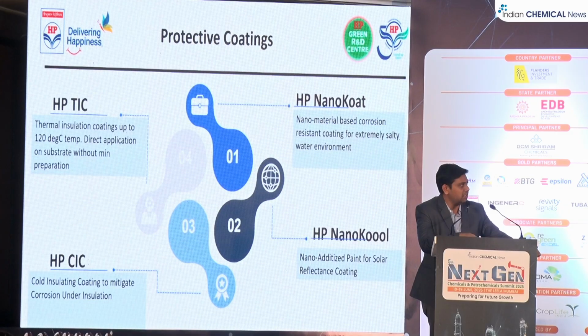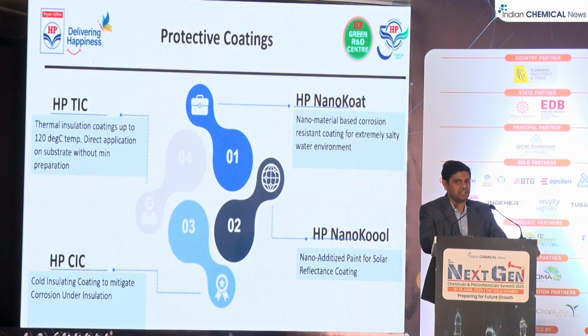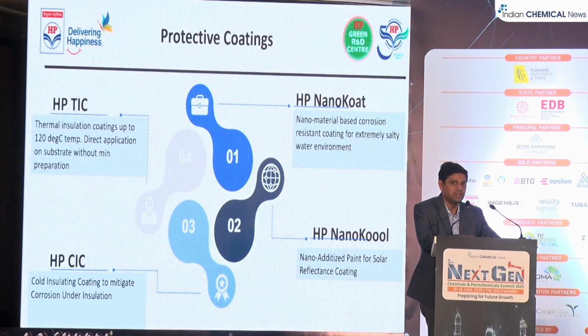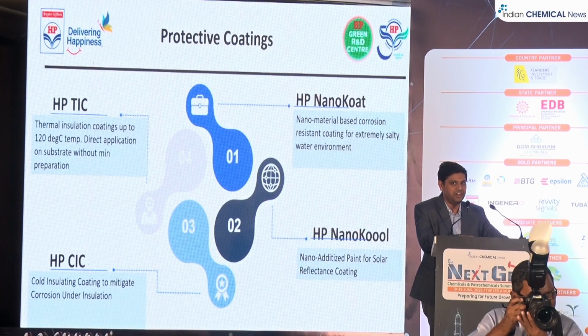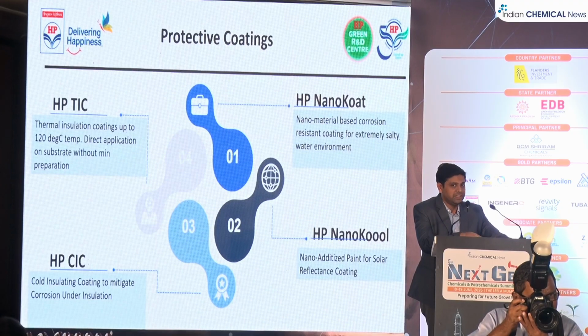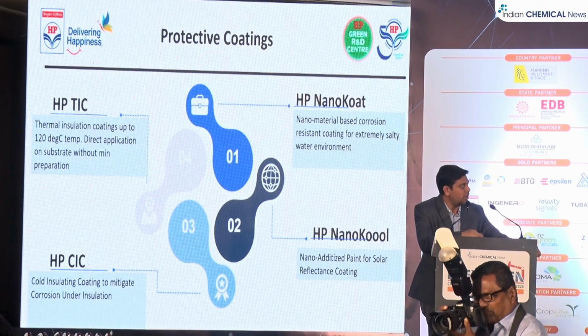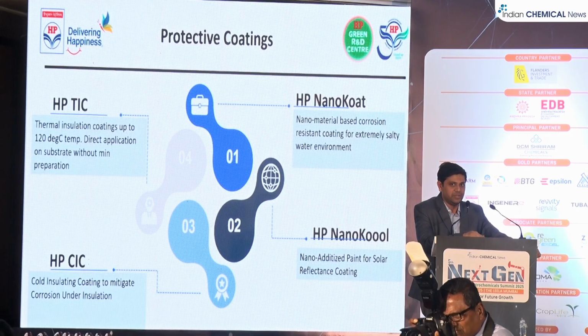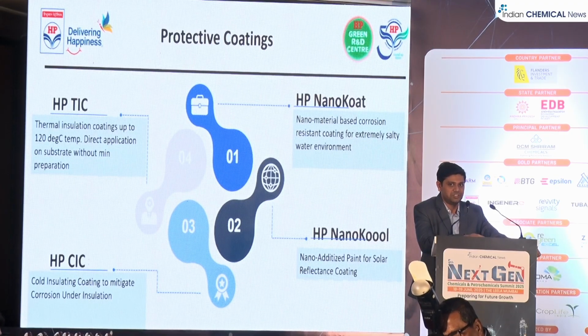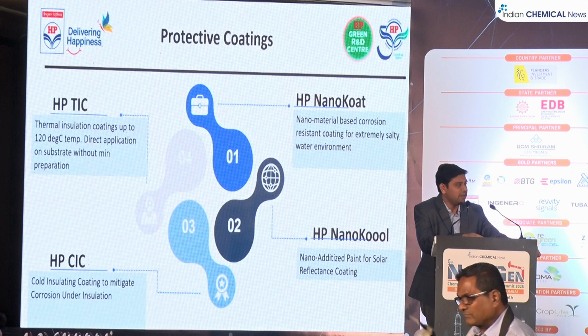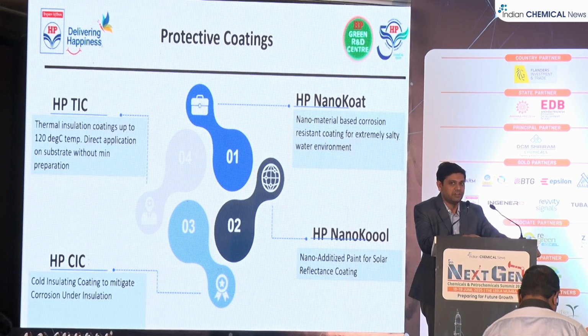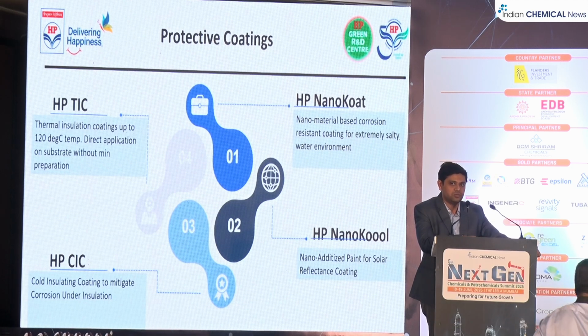We have seen that conventional coatings generally have 3 layers: the sacrificial layer, then a middle layer, and the top UV resistant layer. But by using nanomaterial, only one coat is needed. It gives the same performance as the three coats, and this nano coat has been used in our refineries where we see a lot of corrosion due to the outside environment, and it has worked perfectly.